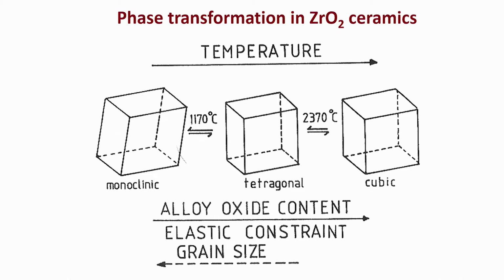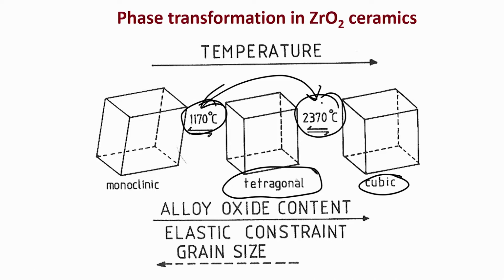Now, as far as the typical phase transformation temperature is concerned, the cubic phase is stable above 2370 degrees Celsius. Between 1170 and 2370, it is the tetragonal phase which is stable, and below 1170 degrees Celsius up to room temperature, it is the monoclinic phase which is stable. So, these are the three major polymorphs of zirconia. Now, as I said, this alloy oxide content is nothing but dopant content.